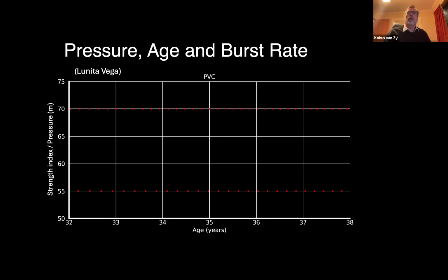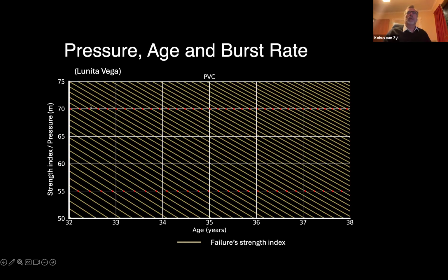And so we drew these lines. Now, each of these lines represents an individual leak in a DMA. And when the line crosses the pressure in the system, that leak becomes discoverable. So what this shows is that this leak was discoverable at year 32 at 70 meters. But if the pressure is 55 meters, it needs to grow the crack or develop the hole. And so it's going to take more time, and maybe only 2 or 3 years later, we will discover it at 55 meters. So this was our conceptual model for leakage.